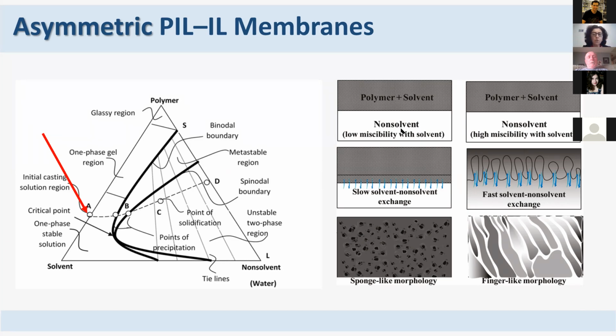So the key here is to choose the solvent, because the non-solvent typically is water. So what we want is to have very low miscibility between the non-solvent and the solvent. If we have a very low miscibility, we will have a slow exchange of the solvent for the non-solvent, and we end up with a sponge-like morphology. Otherwise, if we have a high miscibility of non-solvent and solvent, we have a fast exchange and we'll get a finger-like morphology. And I'm going to show you why this is a problem.